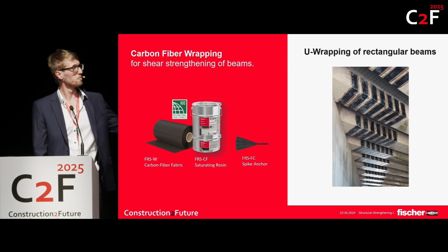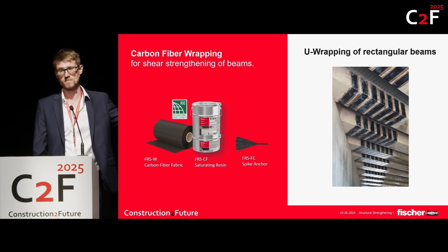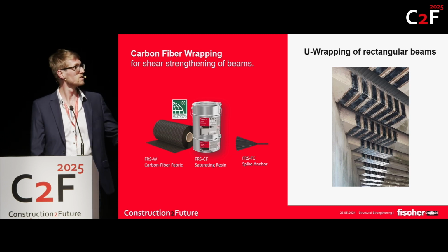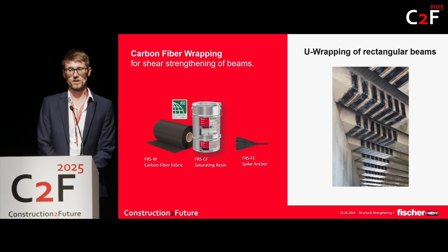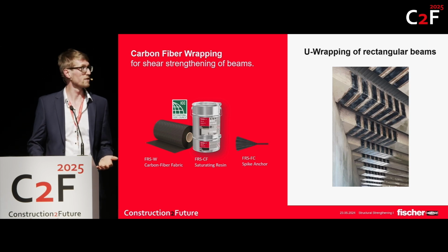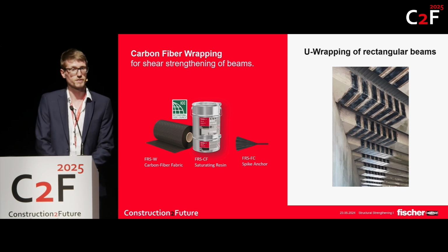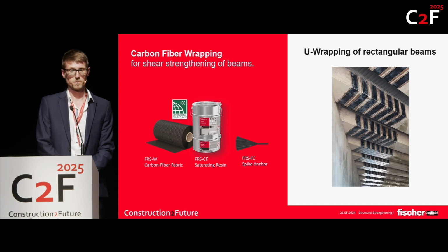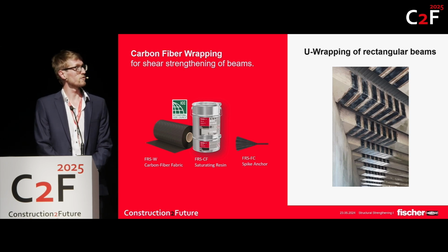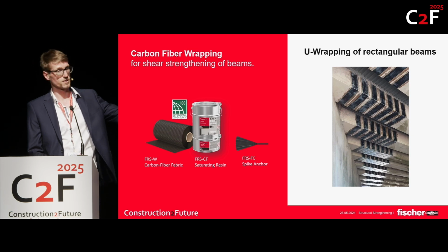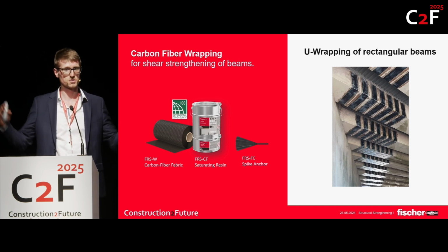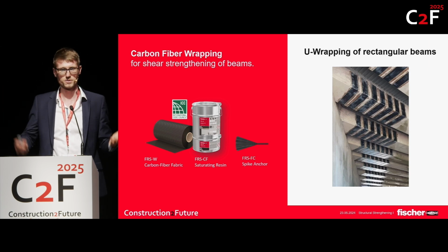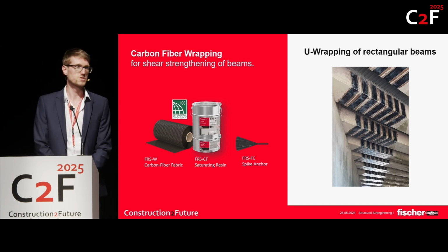Basically the idea is that you bond the pre-cured part into a drill hole with our FIS EM Plus epoxy mortar, for example, and with the open end you can laminate on the fabric in order to prevent debonding, which gives you a larger scope of applications. You can have concave shapes that you can retrofit with the fabrics with this technology, and also you can have end anchorage of fabrics in shear strengthening, because I think Professor Bergmeister said you have to close the load loop. He was referring to another bridge structure, but actually that's what he meant, and it's one suitable solution which is also more convenient in application than most products on the market.